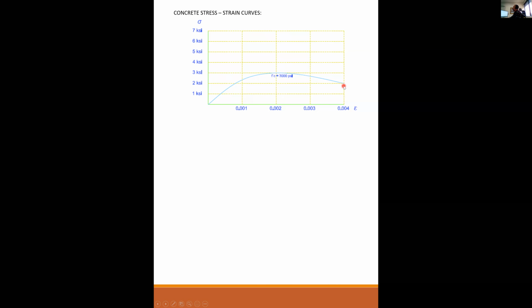And from there, it just starts degrading, right? So the more you keep compressing it, you don't get as much strength. It's basically on its way to just crushing or destruction. But it does sustain a fairly large strain, even though it's not carrying as much load anymore. As we go to a 4000 PSI mix, it maxes out at 4000, as you can see. It maxes out at about the same point, 0.002, but notice that it falls off quicker than the 3000. Here we have a 5000. Same idea, it hits the maximum of 5 KSI at about 0.002 on the strain, but it drops off even quicker still, right?